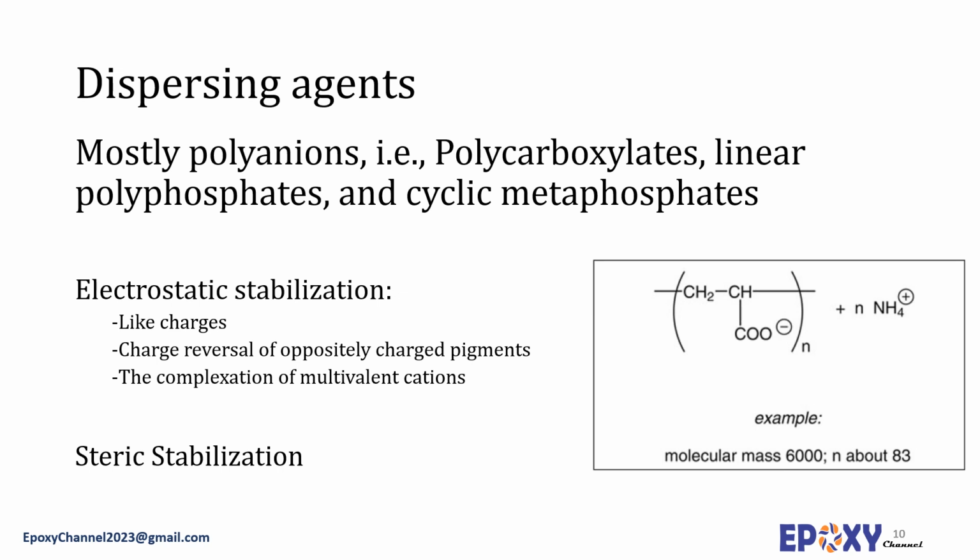The schematic of salts of a polyacrylic acid dispersing agent for waterborne systems has been presented here. There are also polymeric dispersing agents for steric stabilization. In this case, block and graft copolymers are better suited to stabilization than random copolymers or homopolymers. It is worth repeating that here the risk of bridging flocculation should be considered. Moreover, the dilution of sterically stabilized pigment dispersion with unsuitable solvent results in coiling and consequently flocculation.